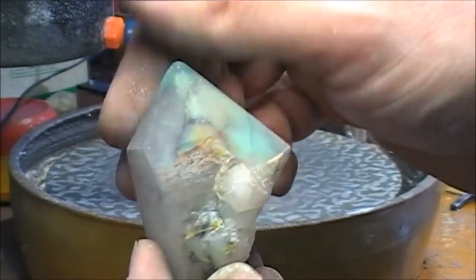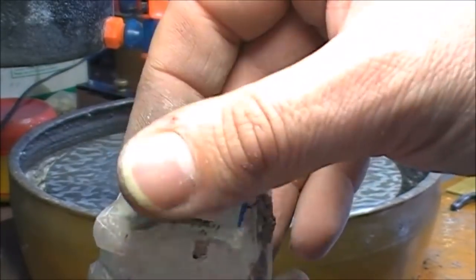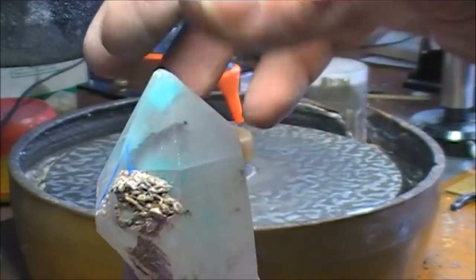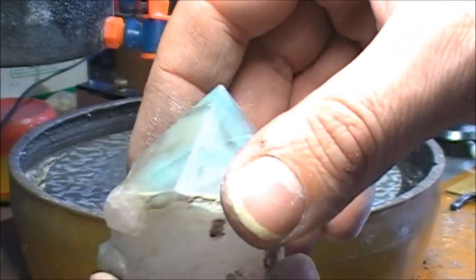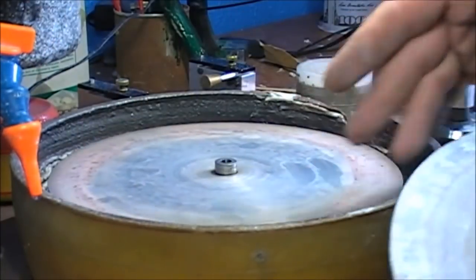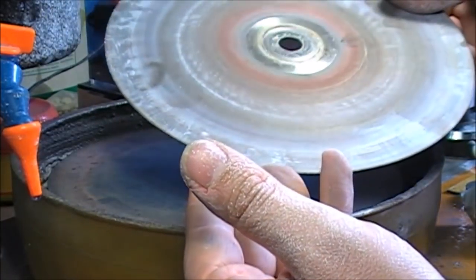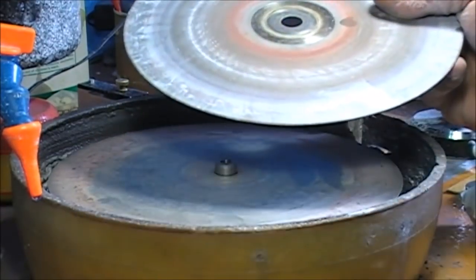As you can see, I cleaned up all the excess material on top of the ajoite. Now we're going for a finer grit to well-define the stone and take up these chips from the top. I'm going ahead using a master lap — this is aluminium — and these thin discs you can buy online in different grits. This is 400 and this is 600. First we go with 400 to smoothen up nicely, and then 600 — that's a pre-polish — and I'll show you the differences.